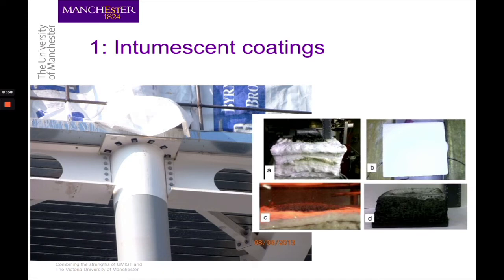So first, I will deal with intumescent coatings. Of course, intumescent coatings nowadays are the most frequently used fire protection materials, certainly in the UK. So this is a tubular steel with concrete fill inside. The white color here is intumescent coating. In this case, the concrete filled tube is unprotected from this level down. Intumescent coating protects steel by expanding after being heated up. That is its main function, or the main mechanism of providing protection.